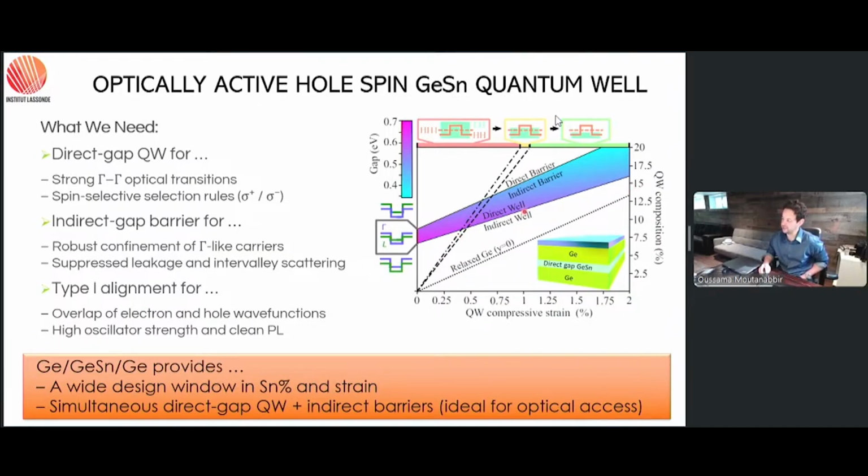So we look now at the band alignment. If I'm to the left of this line, I will have the heavy hole buried in the continuum of the light hole. If I move slightly to this narrow band, I will still have issues with the confined state of the heavy hole. It's still close, buried in the light hole continuum, but it's not that bad. There is a small offset between the two.